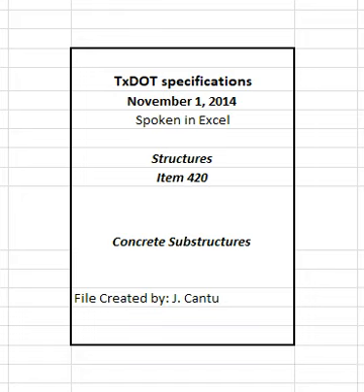4.7.5 Preparation of surfaces. Thoroughly wet all forms and hardened concrete on which concrete is to be placed before placing concrete on them. Remove any remaining puddles of excess water before placing concrete. Provide surfaces that are in a moist, saturated surface dry condition when concrete is placed on them. Ensure the subgrade or foundation is moist before placing concrete on grade. Lightly sprinkle the subgrade if dry.